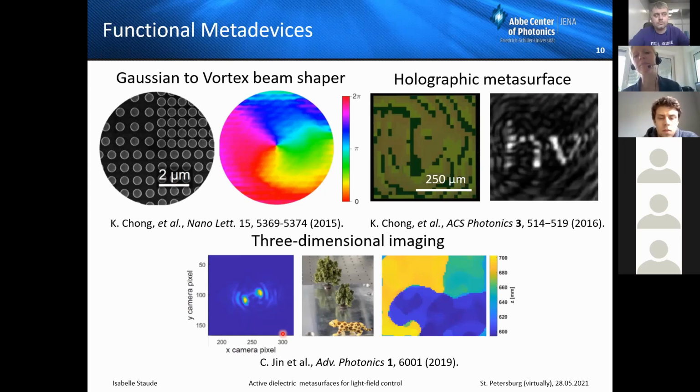And for this, in many cases, we just used parameter sweeps. Because we don't have that many parameters, it's actually quite feasible. In this case, we were fixed to this Huygens regime, which fixes the aspect ratio of the disks. The operation wavelength then fixes the overall size of the disks, and all we had to sweep was basically the lattice constant. So there was no need to use any advanced machine learning for that.